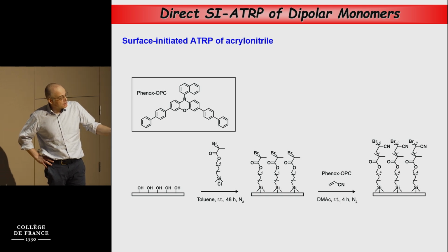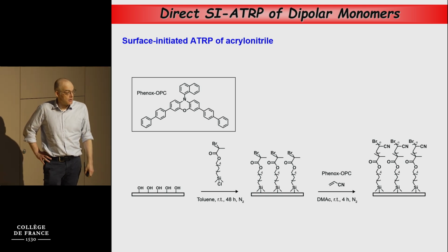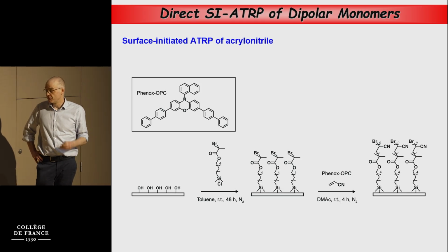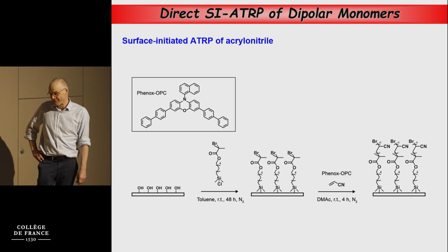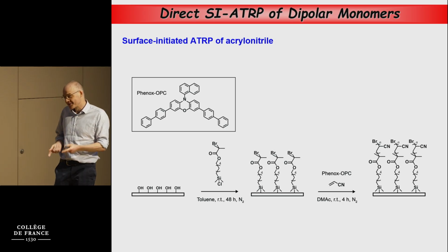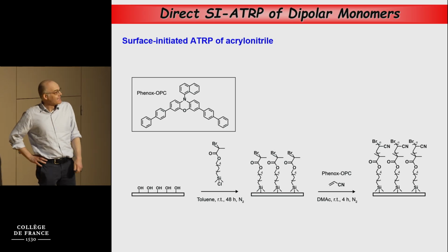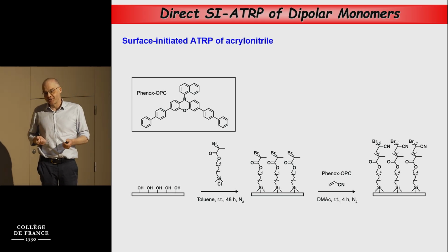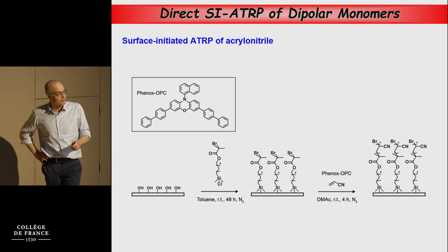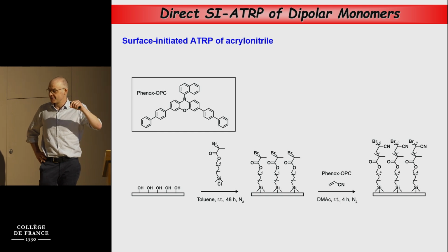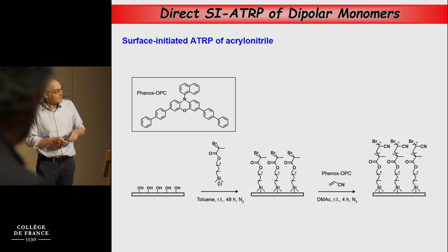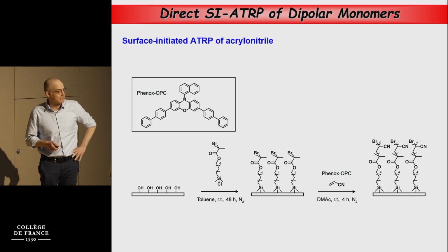We picked acrylonitrile because polyacrylonitrile is a very well-known piezo- and pyroelectric polymer. The first data on these properties go back to the 1970s and 1980s. Sam Stoop worked on this during his PhD with Stephen Carr, if I'm correct. I was looking for your paper, but I had no access this morning, so I have a different paper on the slide. And acrylonitrile is a very interesting system because a nitrile group has a dipole moment of about 3.5 debye. So the rationale was, can we utilize this as a monomer, polymerize this, and see if we could utilize surface-initiated polymerization to somehow induce alignment of these molecular dipoles.